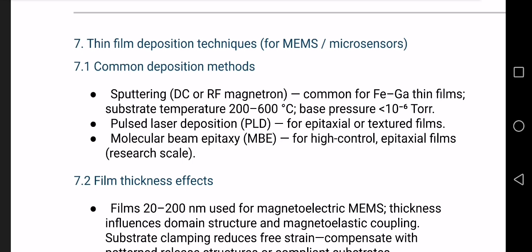First, we have sputtering, DC or RF magnetron sputtering. The most commonly used method for Fe-Ga thin films is sputtering. In sputtering, a Fe-Ga target is bombarded with ions. Atoms are ejected and deposited on a substrate. Typical conditions are substrate temperature 200 to 600 degrees Celsius, base pressure below 10 raised to power minus 6 torr.